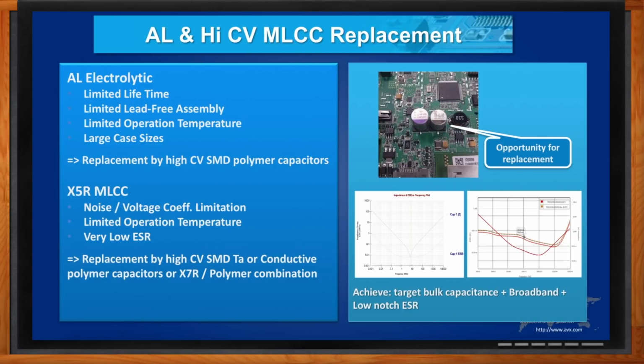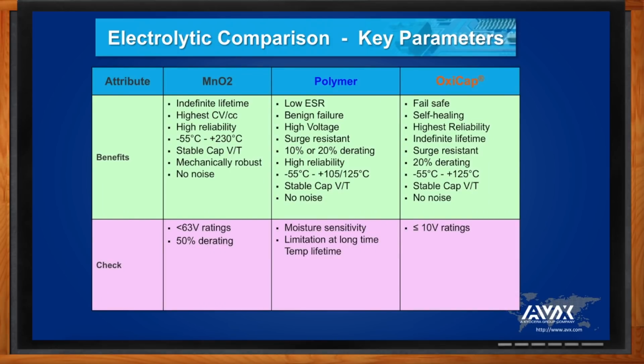So how would you summarize the electrolytic comparison? Well, just as a final summary chart, we have the benefits here for the tantalum polymer and the niobium Oxicap type. The manganese has indefinite lifetime, high CV per cc, high reliability, mechanically robust and no noise. The polymer has got low ESR. This is how to get the low ESR for the tantalum technology, and it has a more benign failure mode. So if you do experience the infant lifetime concern, it's far less of an issue with the polymer. You don't need to derate it as much because it's got a more efficient self-healing mechanism. So 10% or 20% derating compared to a 50% derate for the standard tantalum. Stable temperature characteristics and no piezo noise.